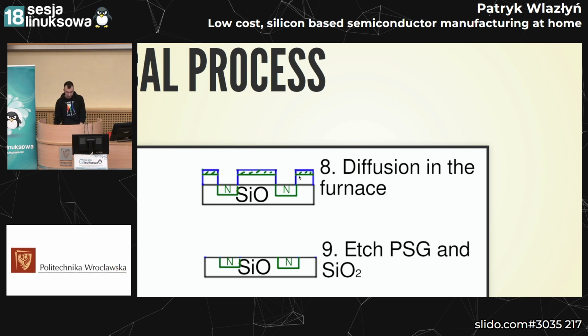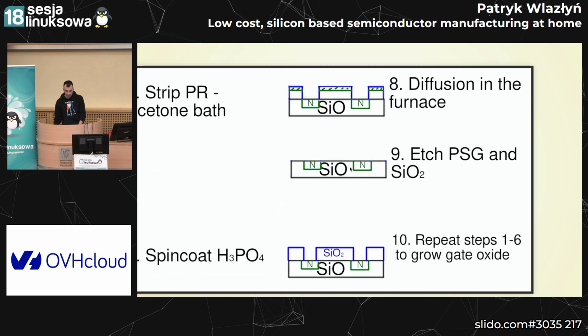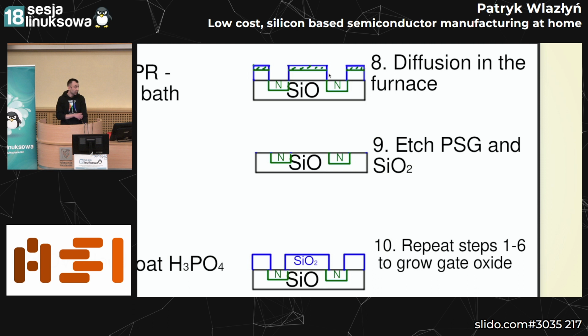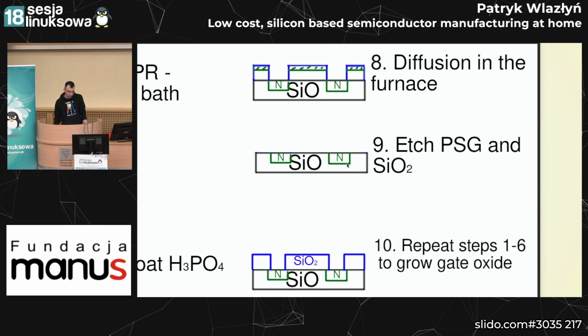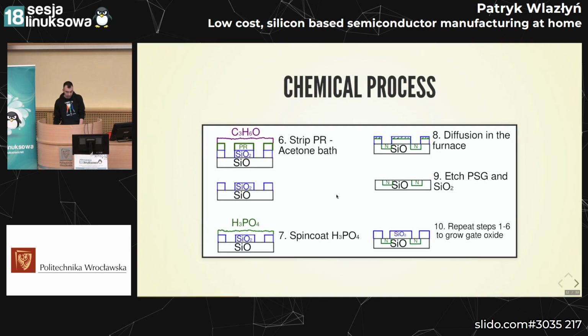And the phosphor atoms will go into the silicon wafer as well as the silicon dioxide layer. But we can etch the silicon dioxide again using the HF solution, for example, leaving the silicon wafer doped only in these two regions, creating two n-doped regions. And a similar process can be used with boron to introduce p-type impurities.